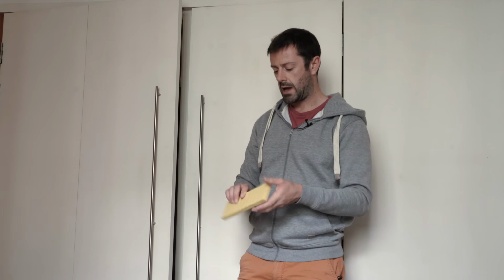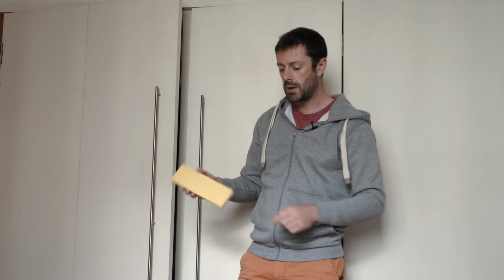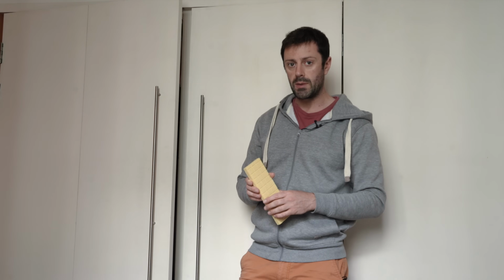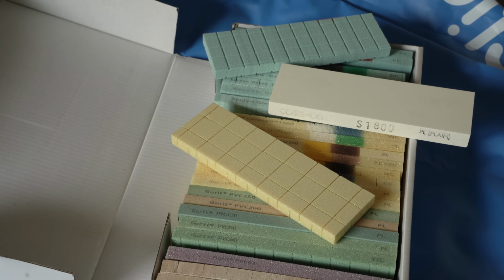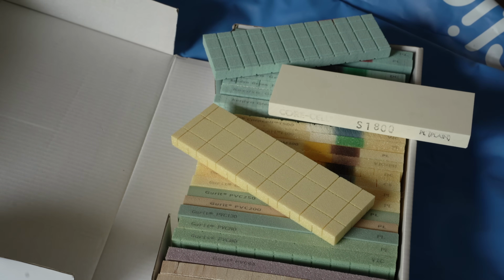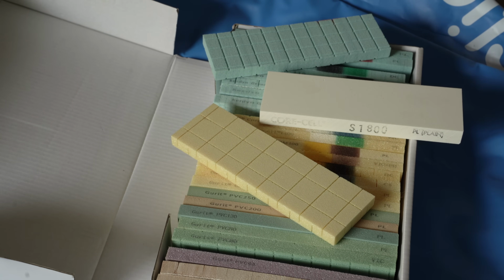And they have it in a load of different types of finish as well. You see that this one has got some shapes in there, and I'll do a close-up to show you what that really means. You can buy foam in plain sheet, which is fine for most wet layups. You simply need to make sure that there's a full, uniform and substantial resin bond adhering the surface of the foam, which is optimized for bonding to the laminate fabric.